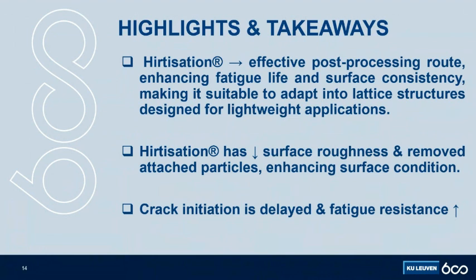Hirtisation® has indeed reduced surface roughness and removed attached particles, enhancing surface condition. And because lattice structures have a high surface to volume ratio, this reduced stress concentration, thus promoting a more uniform load distribution, thus delaying crack initiation, and ultimately increasing fatigue resistance.